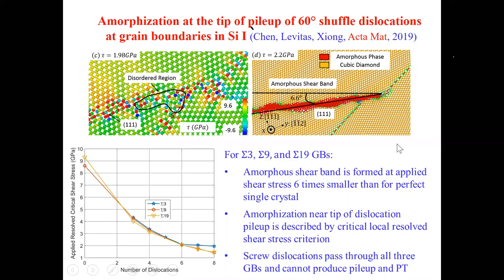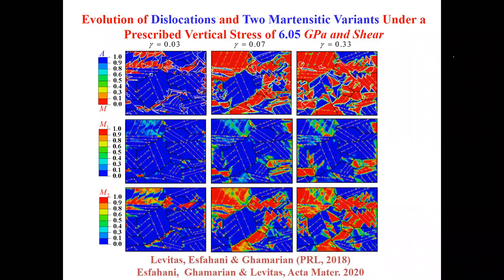We have confirmation from molecular dynamics: there is a dislocation pile-up against three different grain boundaries in silicon with 60-degree shuffle dislocations. For all grain boundaries we obtain the same curve of shear stress necessary for amorphization versus number of dislocations. For example, one dislocation can reduce required shear stress from 9 GPa to 1.5 GPa. Of course, more dislocations can be added. An important finding is that screw dislocations pass through all three grain boundaries — so they cannot pile up and cannot promote phase transformations.